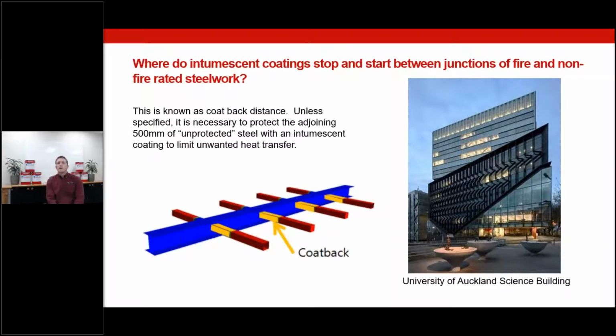Where do intumescent coatings stop and start between junctions of fire and non-fire rated steelwork, or secondary and primary steelwork? This is known as what's called coatback distance. Unless it's specified, it's necessary to protect the adjoining half metre of unprotected steel with an intumescent coating to limit any unwanted heat transfer between the non-fire rated and the fire rated. You'll get various measurements required. If you look worldwide, it usually varies between 300 and 500 millimetres, but we as a collective group, the FPANs, decided on 500 just for the sake of conservatism, and to make sure that you're encompassing all that you need to with regards to that minimization of heat transfer.